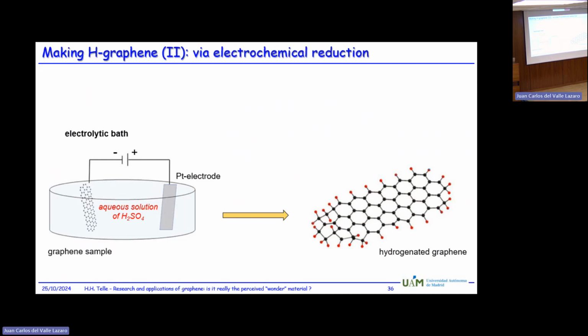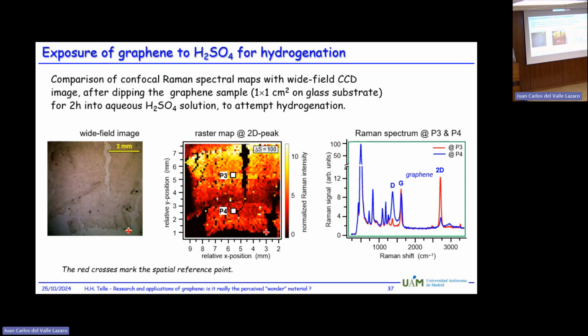You put your graphene as one electrode in the electrolyte and have another metal electrode. You run the current through it, and what you do in that way, you dissociate the H2SO4, and some hydrogen will be there in atomic form to absorb on the sample. So here is the result of our first attempt.